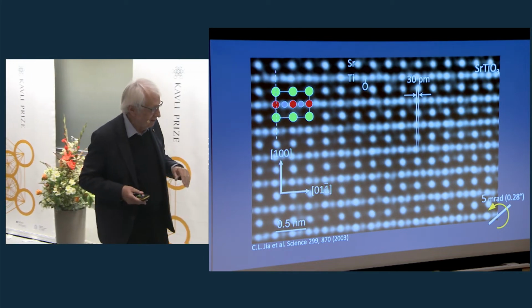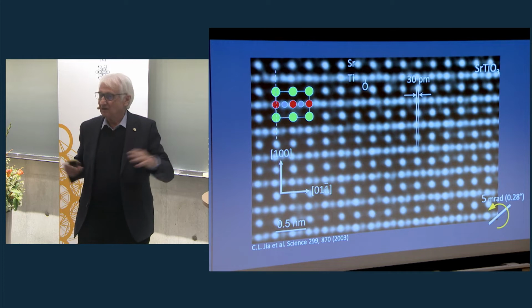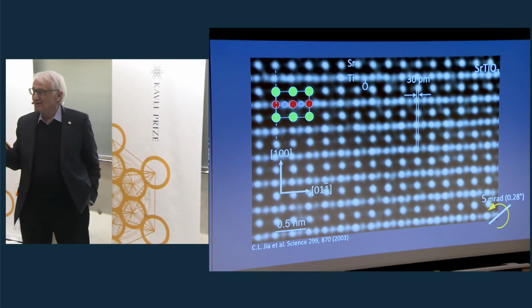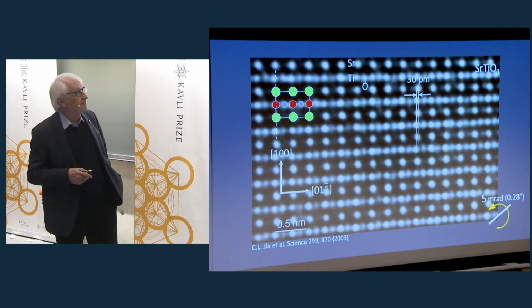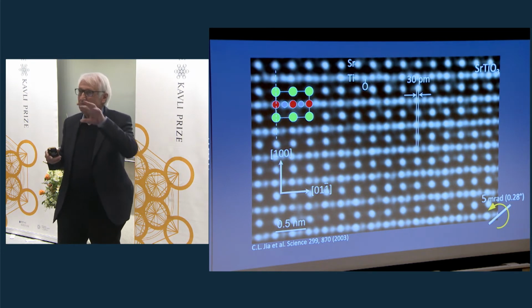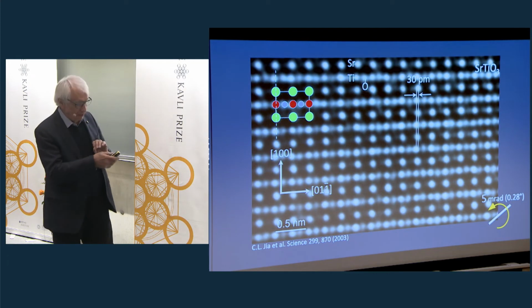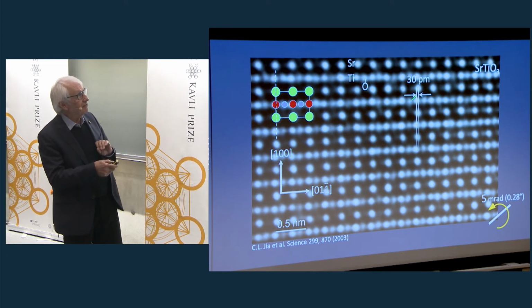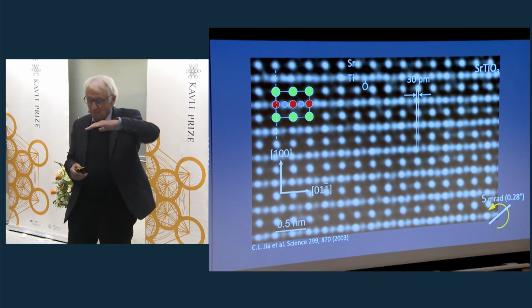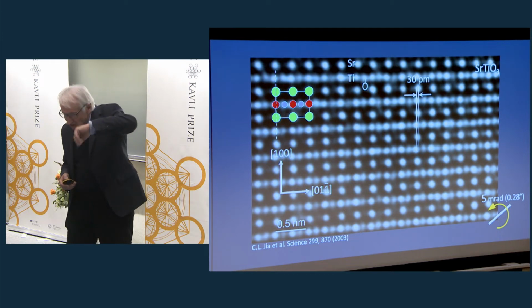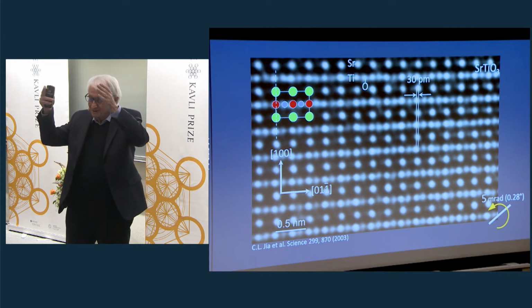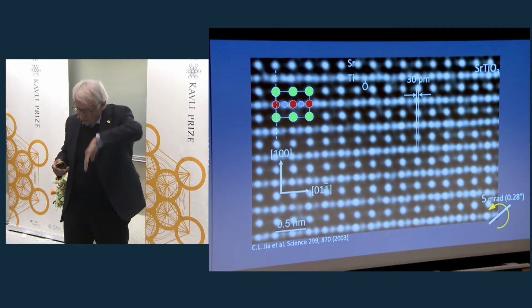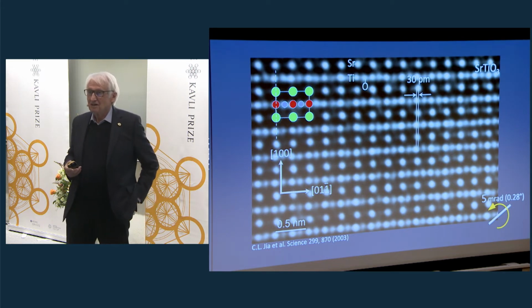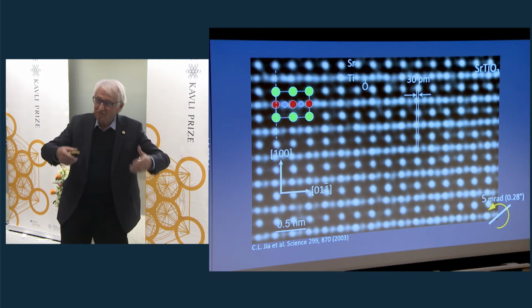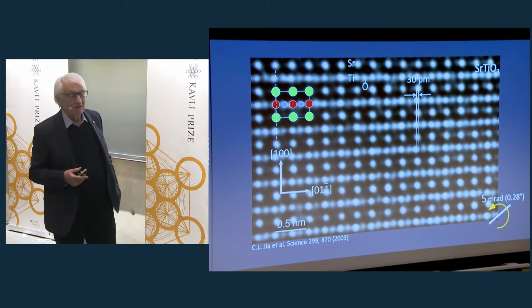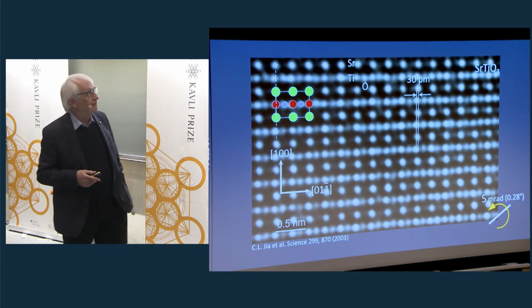You can say, yeah, okay, we just have a projection factor, and that's it. And now that's the trick nature and quantum mechanics are playing on us. The shift for the individual atom is different. It depends on the nuclear charge of the atom. So the shift of strontium compared to that of titanium is different. So titanium shifts, for this 5 milliradians tilt, a little bit more. So this is the result of the electron waves going down the atomic channels, and the quantum mechanics is slightly different quantitatively for titanium and strontium.